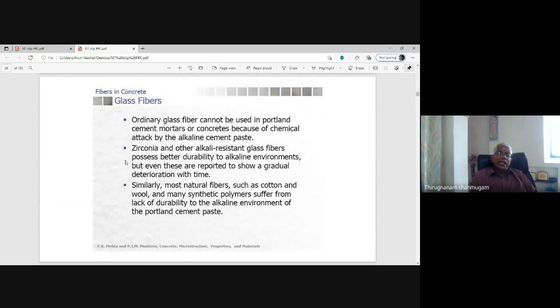If you consider the glass fiber, ordinary glass fiber cannot be used in Portland cement mortars or concrete because of the chemical attack by the alkaline cement paste. The pH value of the cement paste is around 13. So this alkaline nature will affect the siliceous nature of the glass fiber and the chemical reaction will take place and finally the fibers vanish. So you should not use the ordinary glass fiber.